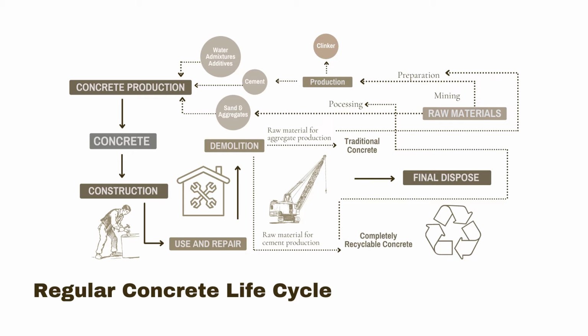All concrete waste is recycled within the cement production process, while for the traditional concrete, the waste scenario was divided according to 2 alternative routes, which include the recycling as concrete aggregate and the final disposal. So overall, the environmental impact of the concrete production process was found to be strongly related to its binder content and its required transport.